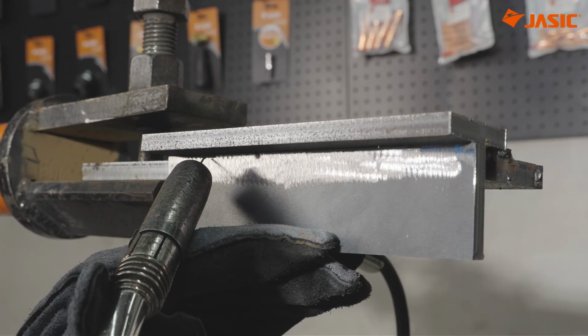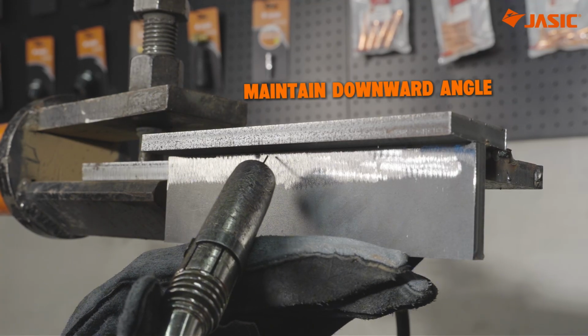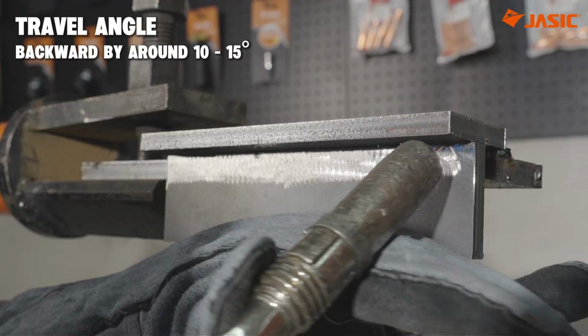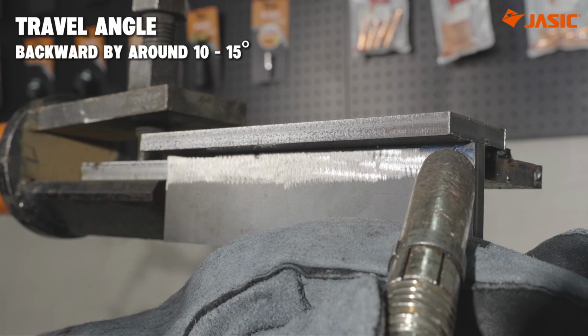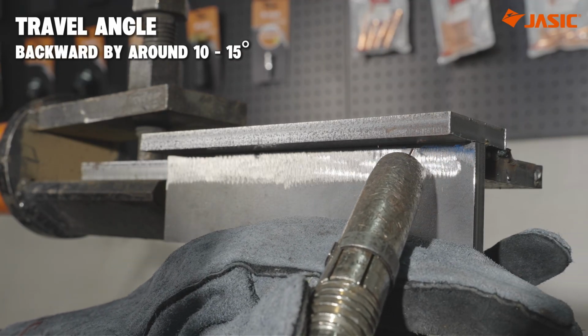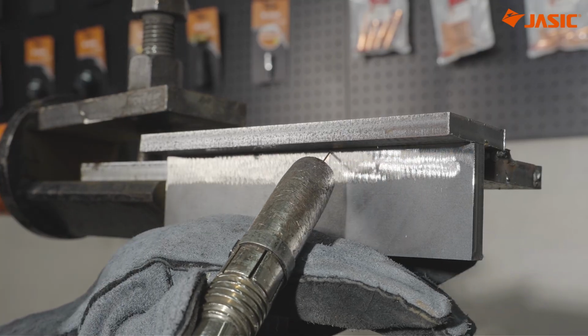Whether you are pushing or pulling, you need to maintain this downward angle to help control the molten pool. As for the travel angle, if you are using the push technique, tilt the gun backward by around 10 to 15 degrees. This allows the arc to work more directly on the root of the joint.